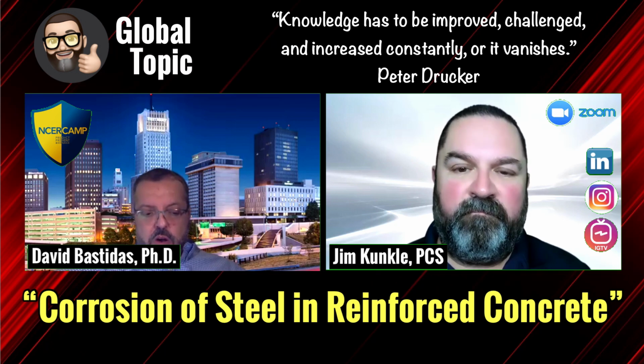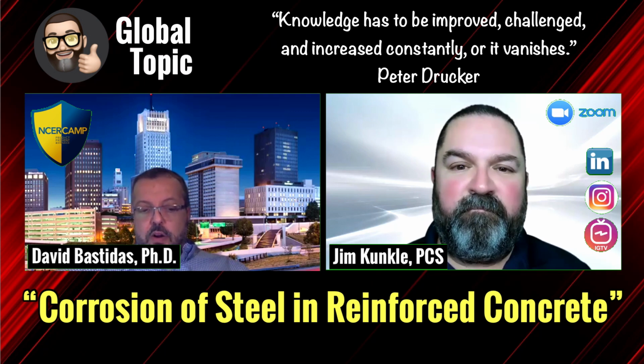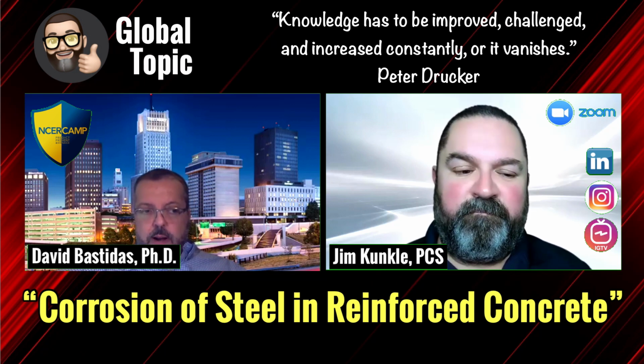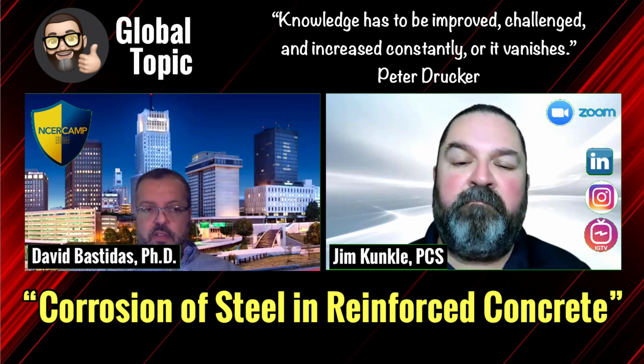Before the passivity breakdown, what is happening is that the chloride at the interface reaches a certain threshold, the chloride threshold, that is the risk. Typically, this chloride threshold in carbon steel is around 0.4. This is why commercial cementitious materials, the typical Portland cement, are regulated by law so that the chloride content needs to be lower than 0.4. So you cannot sell any cement if the chloride content is bigger than that.